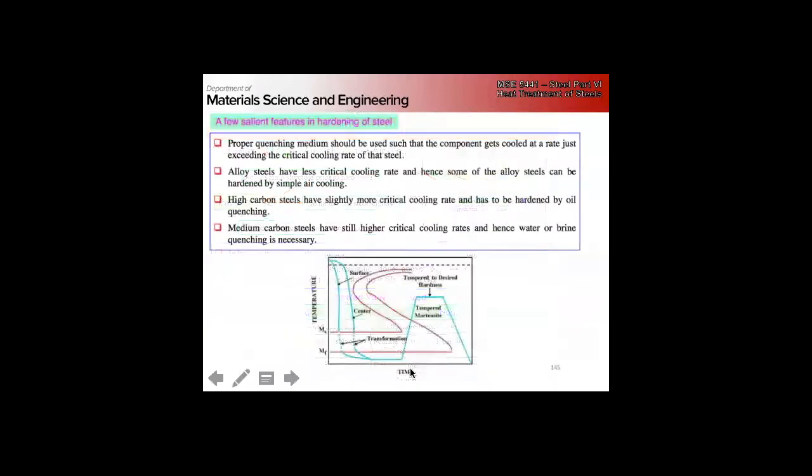Okay, so now on to hardening and tempering. Basically here, we're going to follow a path. Again, we're going to try and miss the front of the TTT curve, come down through the martensite start to below the martensite finish. So now we have a fully martensitic structure. Hold for some time just in case there's a little bit of isothermal martensite that grows.